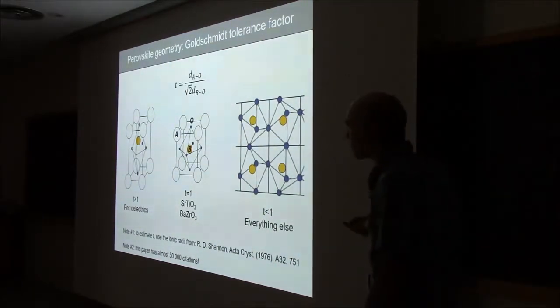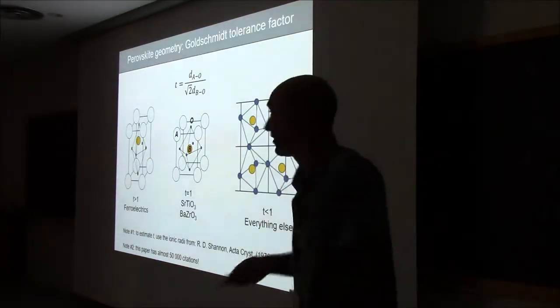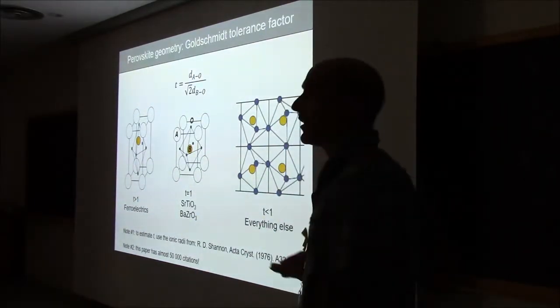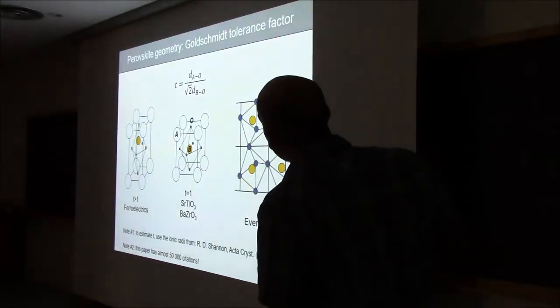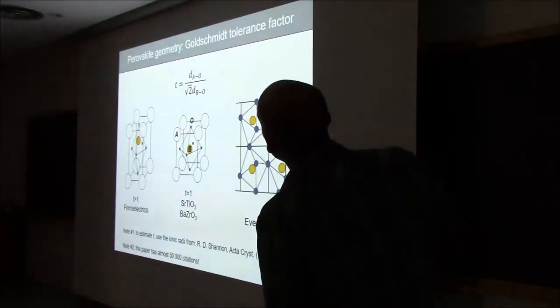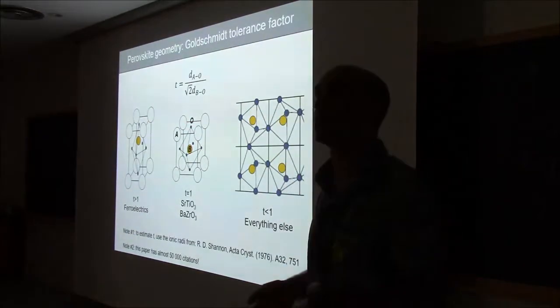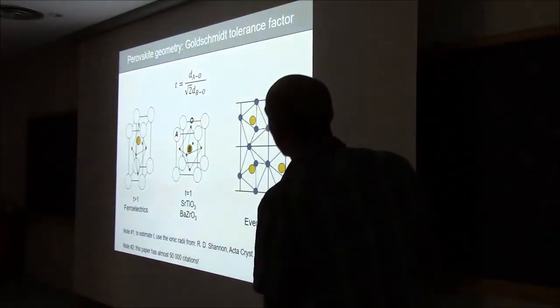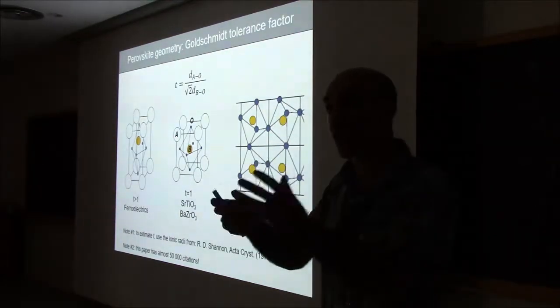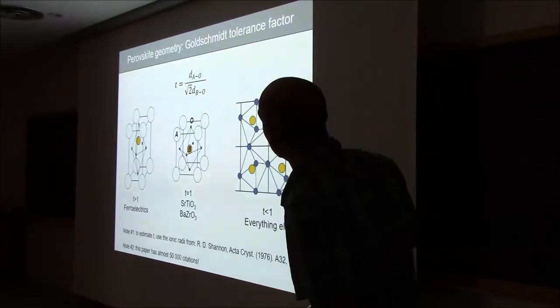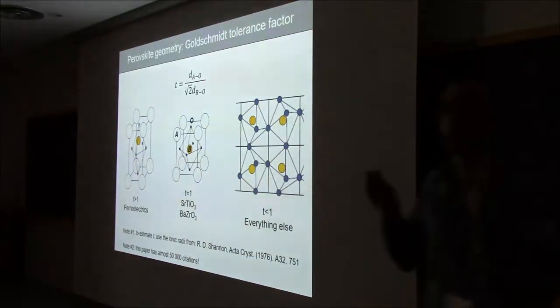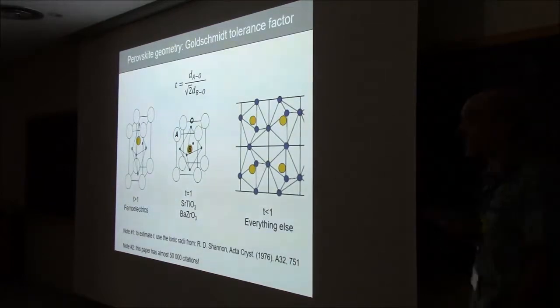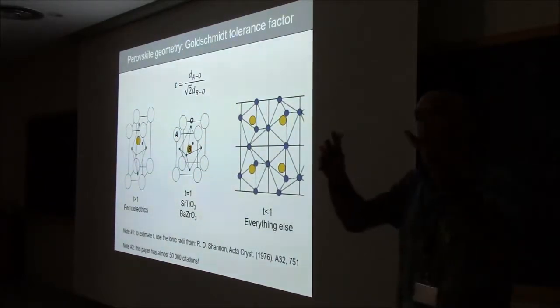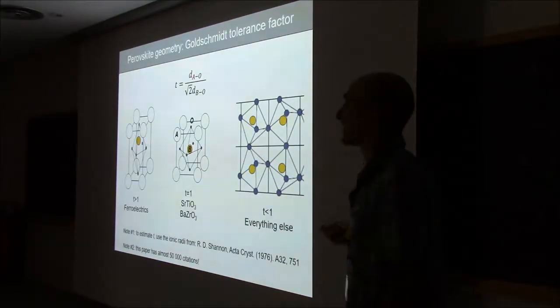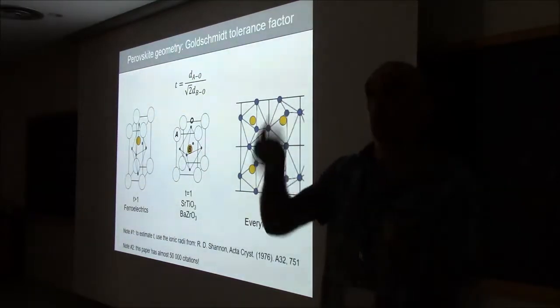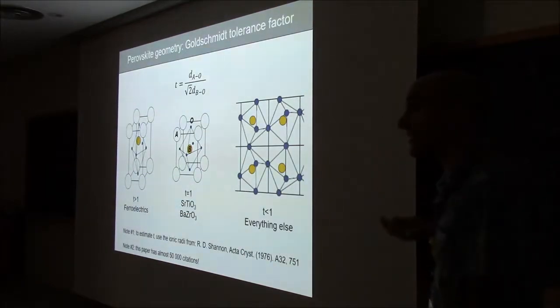Okay? And the first consideration is geometry. If you want to make a perovskite unit cell, you need the distance between the A site and the oxygen to be square root 2 times the distance between the oxygen and the B site. So if the sizes of this ion, this ion and the oxygen are such that this is fulfilled, so that this divided by this gives you 1, then you should have a perfect perovskite unit cell. Strangely enough, because this conjunction of sizes is very rare, it happens very rarely that something would be a perfect cubic perovskite, right? But it does happen at room temperature.